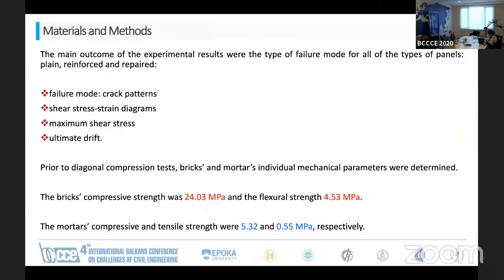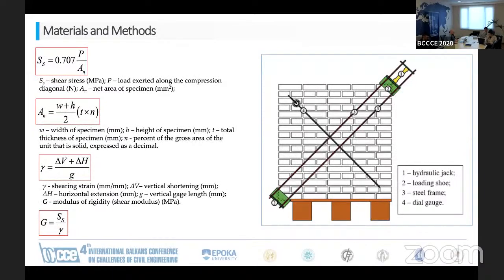Nevertheless, before we made the diagonal compression test, we had to identify the brick and the mortar's individual mechanical parameters. That's why we did tests on these individual samples, and we found out that the brick compressive strength was 24.03 megapascal, the average one, and the flexural strength around 4.53. Whereas for the mortar, we had a 5.32 megapascal compressive strength and almost 1 megapascal tensile strength. However, we already know that in modeling or when we make the analysis for masonry, we assume that the masonry as a whole does not possess any tensile strength. The formulas that are used to calculate all these parameters that we talked about are the ones described in the ASTM E519.